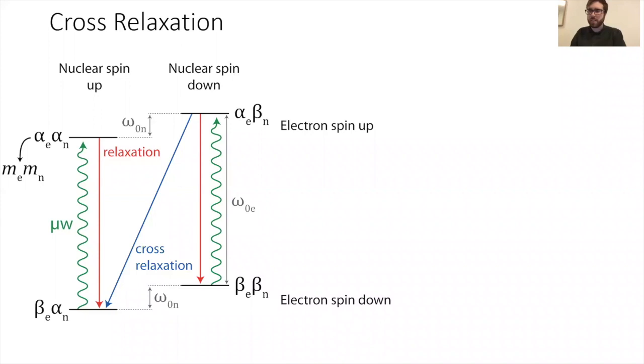Right, and our next question from Quentin Chapuis. How is the spectral density of the electrons in the metal influenced by temperature? Does it end up having an effect on the DNP enhancement? Have you thought about that, Katerina, or do you want me to speculate? Well, I can comment on observations that the DNP enhancement in lithium metal, at least, changes a little bit with temperature, but not much. We tend to see slightly higher enhancement at 100 Kelvin, but the gain we get in resolution at room temperature outweighs that normally.